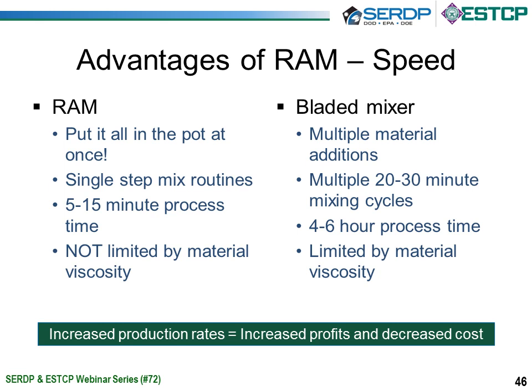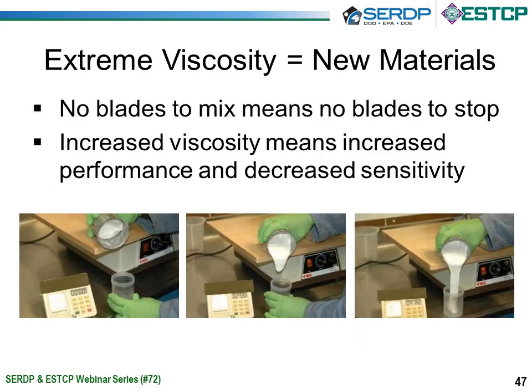You can develop single-step mix routines where you turn the machine on for a very, very short amount of time, and it rapidly homogenizes the material in mixing processes that are as little as 5 minutes. And we're not as limited by material viscosity. Eric mentioned this idea of extreme viscosity materials, which we're going to get to in the next couple of slides. But the bottom line is increased production rates, which you saw in Eric's presentation, is going to equal increased profits and decrease cost overall. If we move on to slide 47, this is what we mean by extreme viscosity.